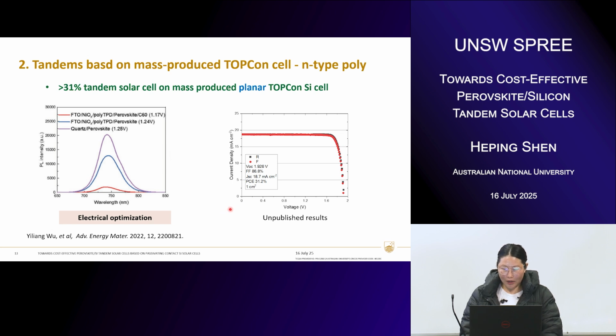But since then we have been moving fast in this field, as you can see in the evolution chart later. We keep on optimizing. There is a lot of optimization, as I mentioned, at the tandem level of electrical optimization. Indicated by our PL study, we found that interfacial recombination between perovskite and charge transport material is a major loss source in our tandem cell. So we spent a lot of time exploring new passivation materials and engineering these passivation processes in a way that further improves the performance and reduces the recombination on these interfaces, which allows us to achieve more than 30, 31, 32% efficiency.